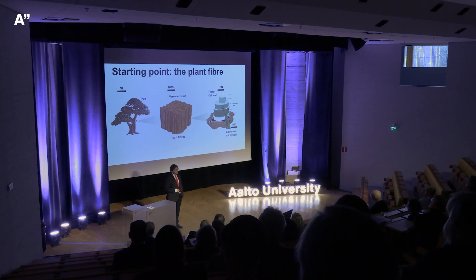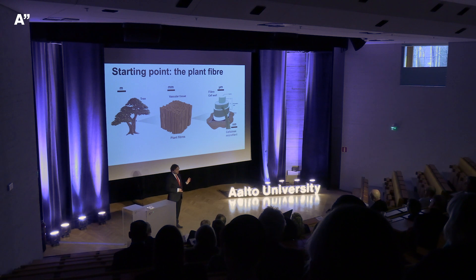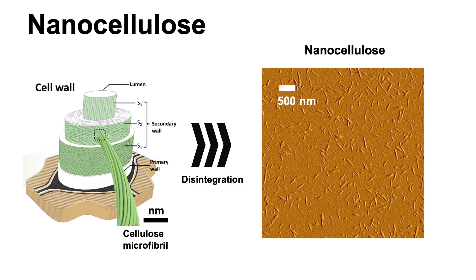There are many components in plant cell walls, and what is the important one is called cellulose. Cellulose is a molecule made of sugar units — what chemists call a polysaccharide. A few cellulose molecules together make these longitudinal threads of very narrow dimensions called cellulose microfibrils. They are just three nanometers in width and consist of just 18 individual cellulose molecules. They give plant fibers their strength and character.